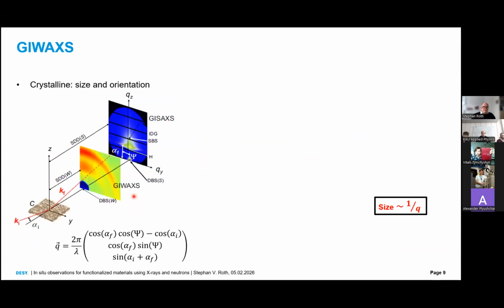And then, like in normal SAXS and WAXS, you can position your detector close to the sample, like 10 to 30 centimeters, or farther away, 1 meter, 2 meters, 10 meters, 13 meters. And then we distinguish again between grazing incidence wide angle X-ray scattering and grazing incidence small angle X-ray scattering. And when we start with the GIWAXS, this is this image here. This is like classical Bragg scattering or diffraction.